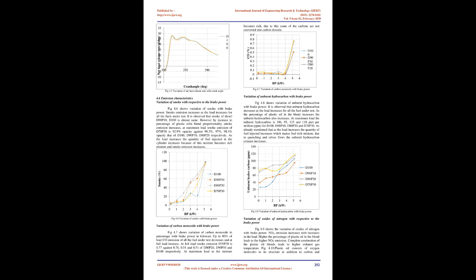It is observed that the density and calorific value of plastic oil are lower and the kinematic viscosity is higher than those of diesel. The density, calorific value, and viscosity of plastic oil are 82.9%, 80.88%, and 184.65% of those of pure diesel. The viscosity of plastic oil, though it is 184.65% of that of diesel, has sufficient value to obtain better spray and penetration. Flash and fire points of plastic oil are well comparable with those of diesel.